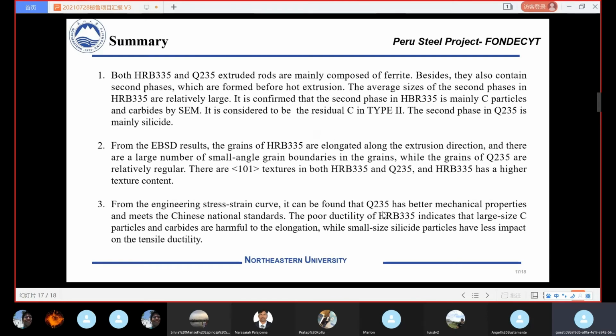Here is the summary of this report. Both the HRB335 and Q235 extruded rods are mainly composed of ferrite. Besides, they also contain second phases, which are formed before hot extrusion. The average size of the second phases in the HRB335 is relatively large. It is confirmed by SEM that the second phase in HRB335 is mainly carbon particles and carbides. It is considered to be the residue carbon in the type 2 powders. The second phase in the Q235 is mainly silicide.